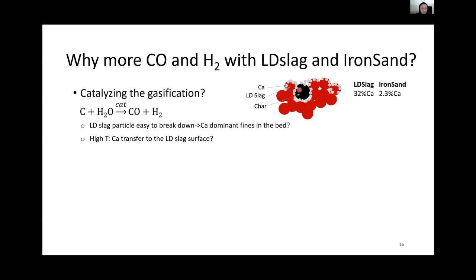So when it's in a fluidized bed, I mean, it's bubbling fluidized, but it's not a fast fluidized bed, so the char particle can be immersed in the bed. It can have a chance to contact with the calcium, and then the gasification is enhanced. A second explanation can be the carbonation reaction. So this reaction, CO2 plus calcium oxide, we get calcium carbonate.